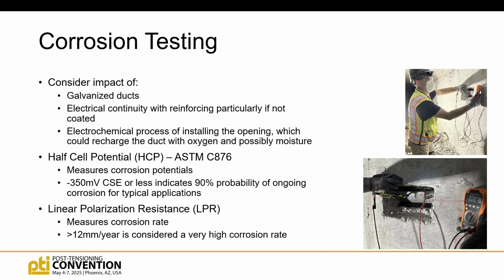So the challenge with these ducts, and like all pre-stressed structures, frankly, is you don't know: is it the galvanized duct that's corroding? Is it the strands that are corroding? Is it the bars that are touching the ducts, which are touching the strands, that are corroding? So you do have to be a bit careful about how you use this data. There are also some modifications based on the amount of the multi-strand systems that you engage in the test. So there's just some complexity there.